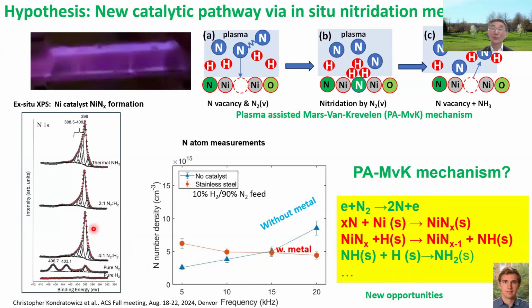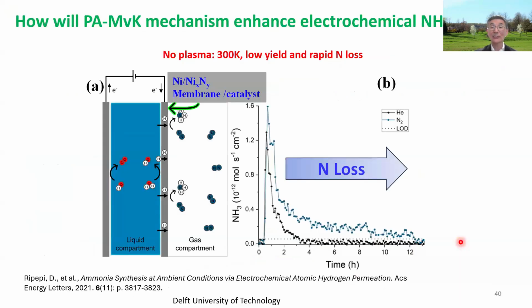Why? If you measure the N atom in the plasma with metal, you see the N atom is decreased. It seems like the N is getting into the metal. So these two experiments suggest that electrons dissociate or excite nitrogen, and excited nitrogen can react with metal to form a surface nitride. It creates a new reaction pathway and can potentially reduce activation energy. So if it is true, how can we demonstrate it? Then we looked at the literature.